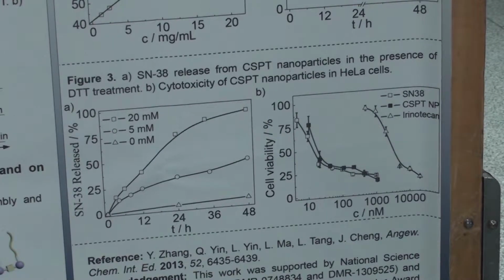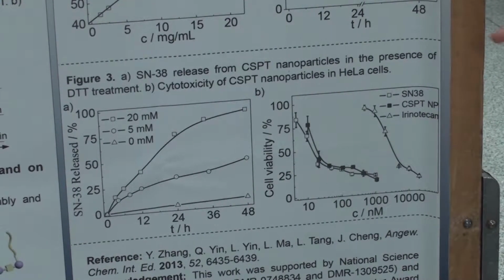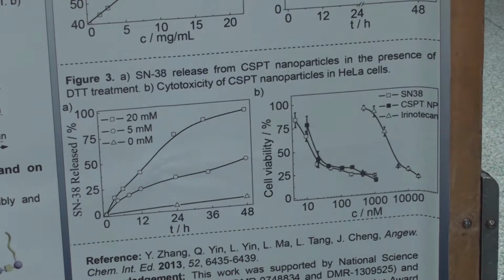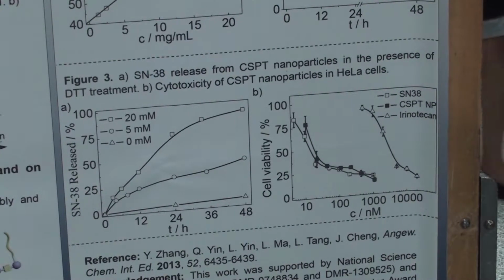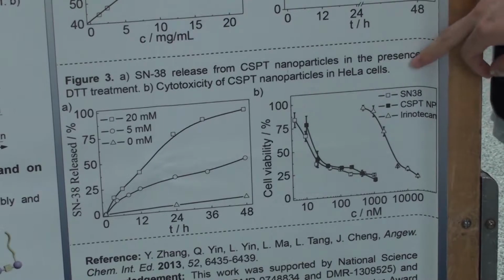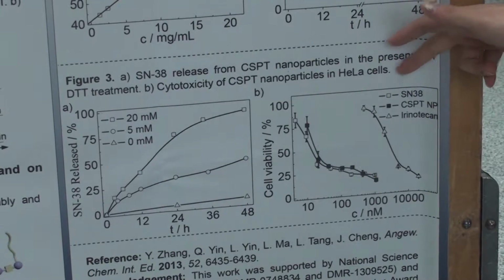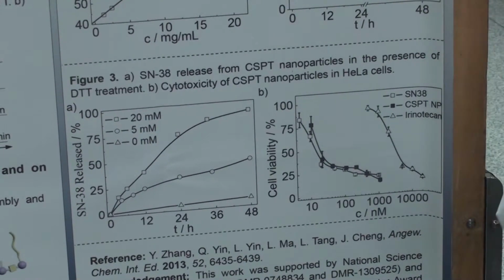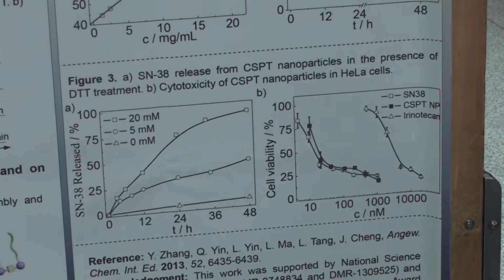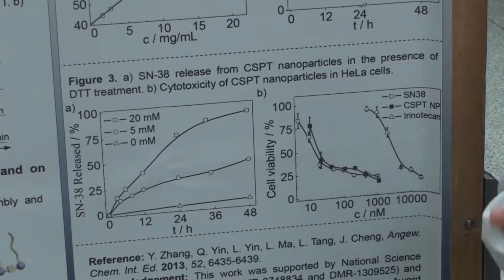We found that our particle system is 100 times more toxic than the clinical use drugs, and also has comparable toxicity to the drug we use as the precursor of the nanoparticles, which means that our system can efficiently release the drugs and be taken up by the cells at a very high level.